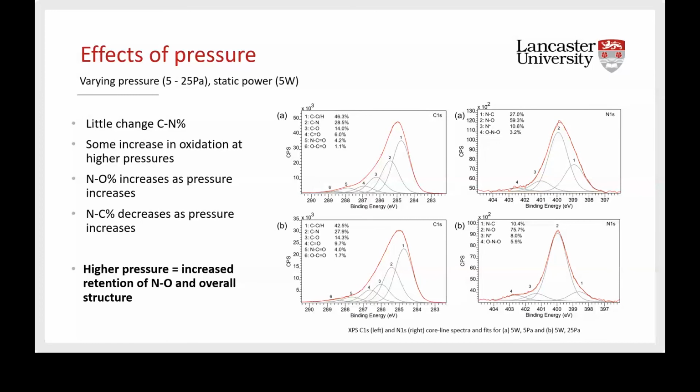So between those two series, we can say our data indicates that higher pressure, lower power allow us to increase retention of that nitrogen-oxygen bond and likely the overall structure. And that's what we're aiming for for the particular application in mind.